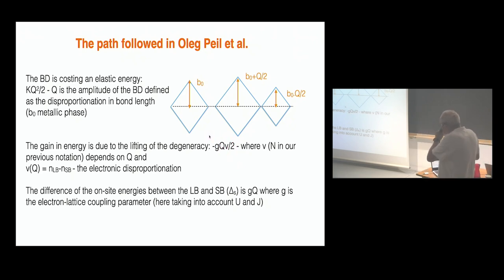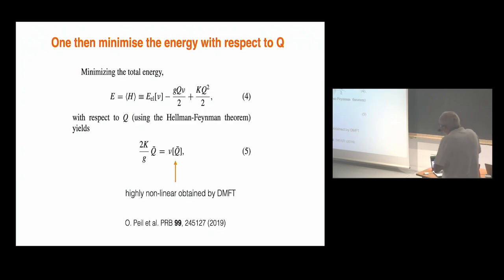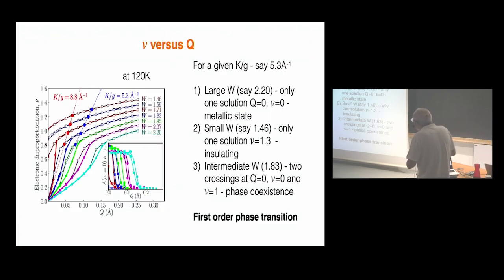So what does it mean? It means that you're gaining an electronic energy which is proportional to the fraction of electrons which will move to the long bond. And the gain in energy is also proportional to this delta S, which is linked to Q. So the calculation is performed this way. You have the energy of the system, the gain in electronic energy and the cost in elastic energy. You minimize this energy with respect to Q, and you find this equation. So 2K over g, okay, constant, times Q, which is our order parameter, is equal to nu of Q, or n of Q, which is highly nonlinear and obtained by DMFT.